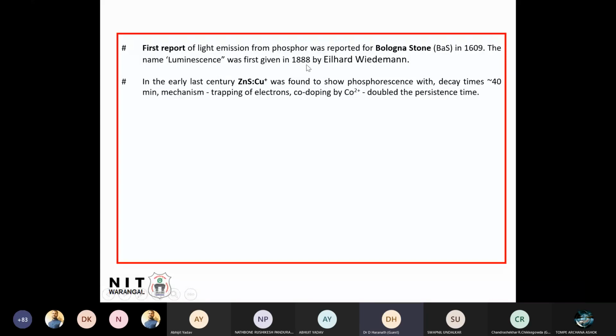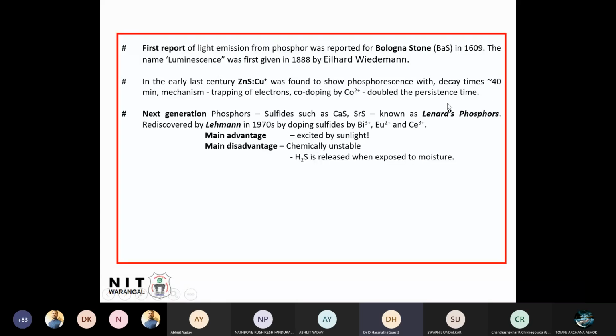Okay, so after barium sulfide, scientists started working on zinc sulfide, another sulfide material doped with copper. With this one, people could achieve about 40 minutes of decay time. Here, a few minutes only. So 40 minutes, and by adding a little bit of cobalt, again they could improve it to about 1 hour, 1 hour of glow in the dark, completely dark. So it was having a great advantage, these types of sulfides.